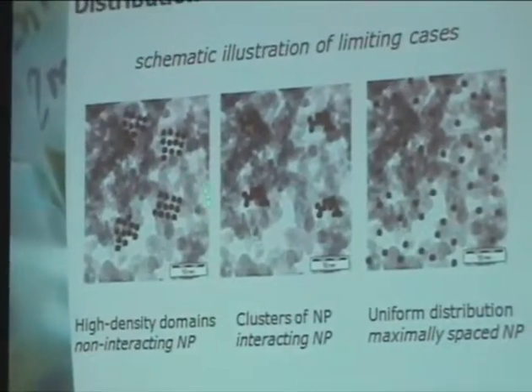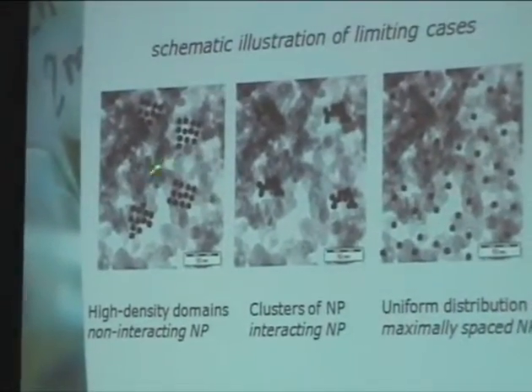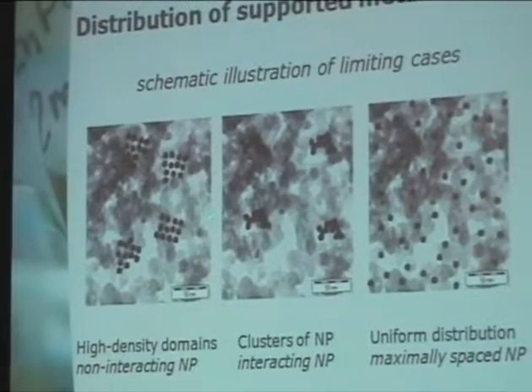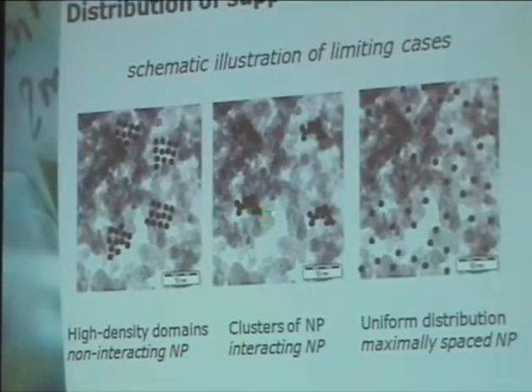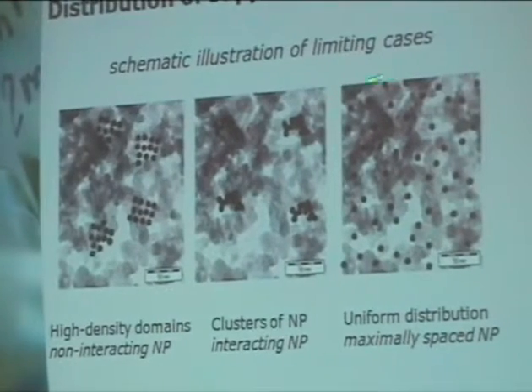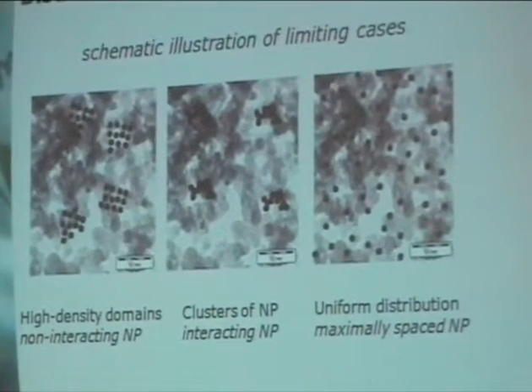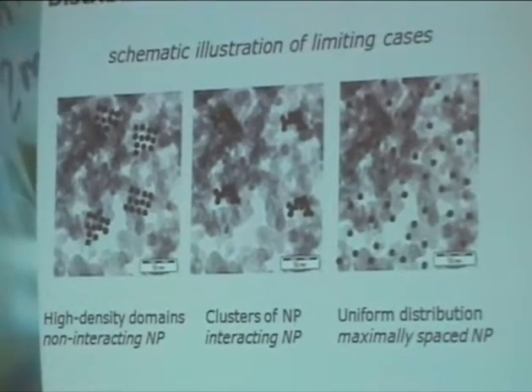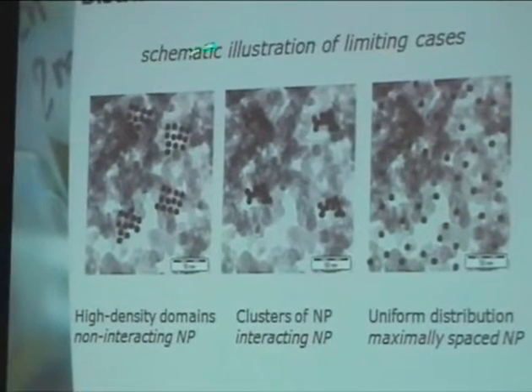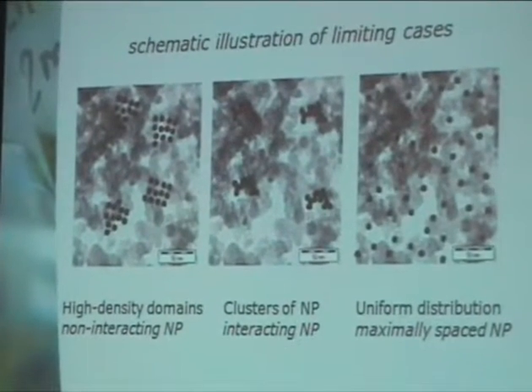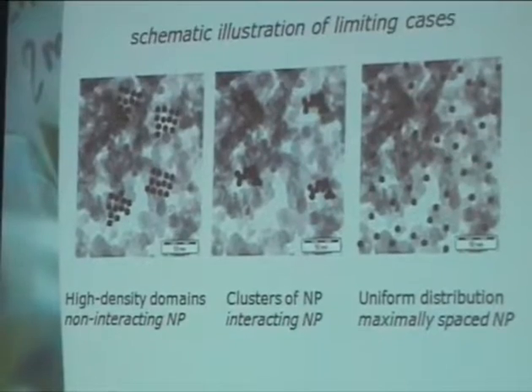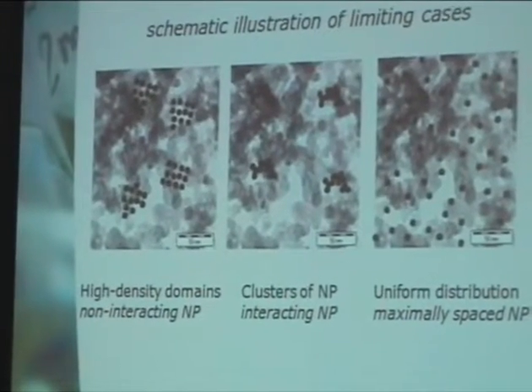One is what I call high density domains of nanoparticles. One is clusters where the particles interact directly with each other, and uniform distributions of nanoparticles. And this has an impact, and we will discuss this for cobalt and also for iron, how this affects the performance of these catalysts.